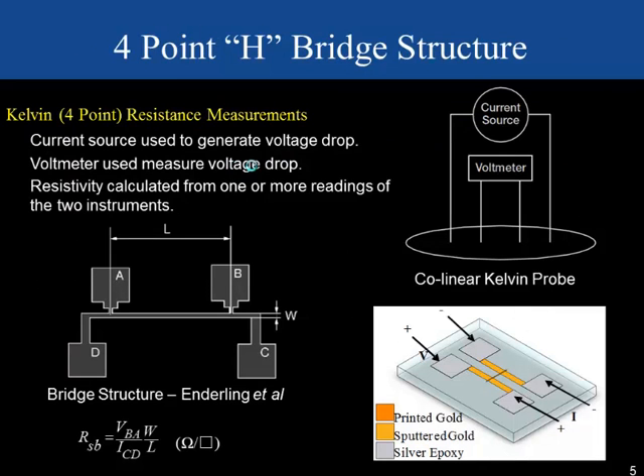However, monitoring this resistivity poses some challenges. Four-point or Kelvin resistance measurements are commonly employed in the microelectronics industry for standard films, and this typically uses a collinear four-point probe, which is readily placed on large area wafers. Unfortunately, for our processes, we are only placing material in small sections, so that would make alignment difficult, and as we're starting with an organic film, contacting it directly would be a challenge. Fortunately, Enderling et al. have put forth a linear bridge structure, which allows for the simple measurement of the sheet resistance of a bridge if the length and width are known, using this relation here. And then if you also know the thickness, you can back out the resistivity.